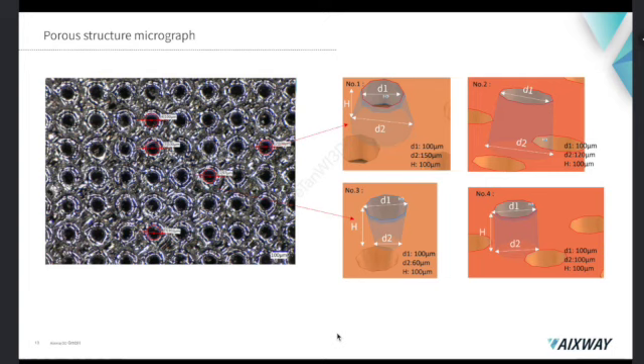And here are some typical structures we have successfully achieved with the micro-LPBF. For example, the porous structure here. We can directly print porous structures with a diameter of 100 microns, and the overall tolerance is about 2 to 3 microns. As you can see here in picture 1 to picture 3, in addition to regular porous structures, we can also print irregular structures like shaped porous.